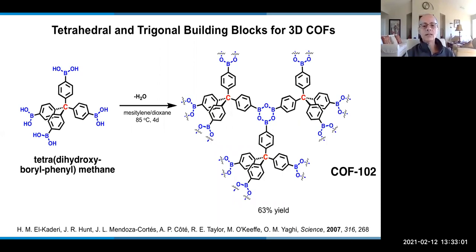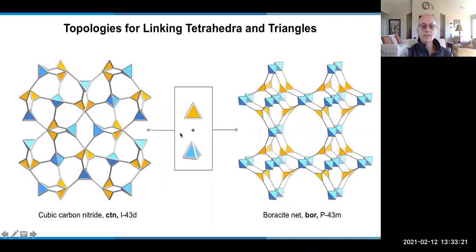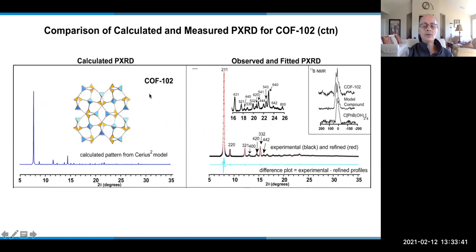To get to 3D COFs, you use tetrahedral building units and the same functionality to make the boroxine ring. So now you have same conditions as I showed before, tetrahedra linked by, the linkage is a triangle, and from MOF chemistry, we know what are the best or the most symmetric structures that would result from combining triangles and tetrahedra. We have the so-called cubic carbon nitride structure, the CTN, and we have the BOR topology, okay? And we can make both, okay? This is the COF-102 structure. You can see the X-ray powder diffraction is fairly sharp.